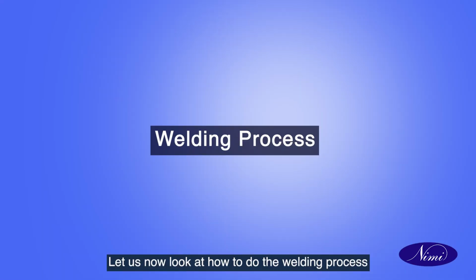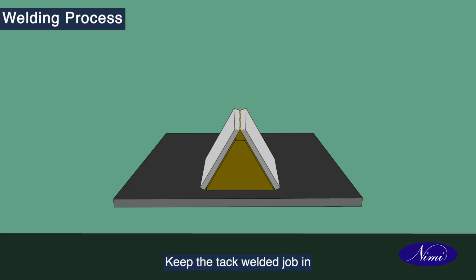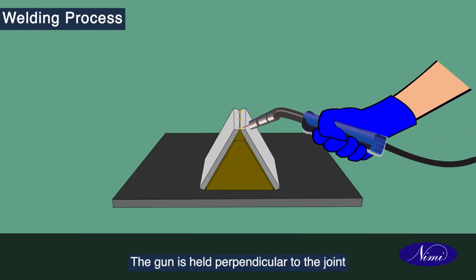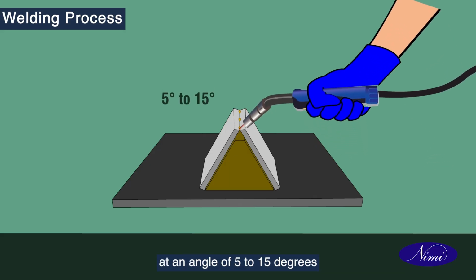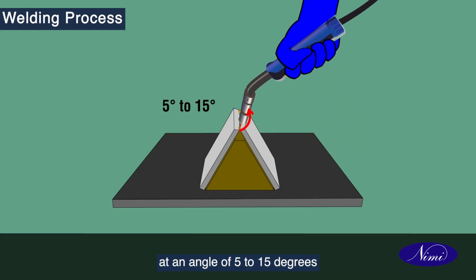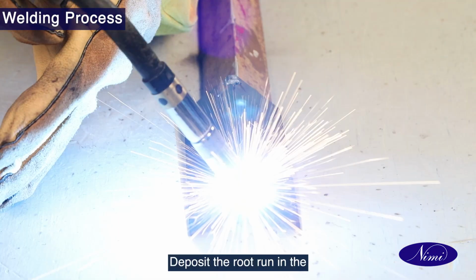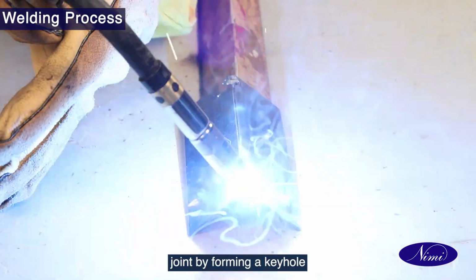Let us now look at how to do the welding process for an open corner joint on an MS sheet 2 mm thick in flat position using gas metal arc welding process. Keep the tack welded job in flat position on the welding table. The gun is held perpendicular to the joint at an angle of 5 to 15 degrees forward to the direction of travel. Deposit the root run in the joint by forming a keyhole.